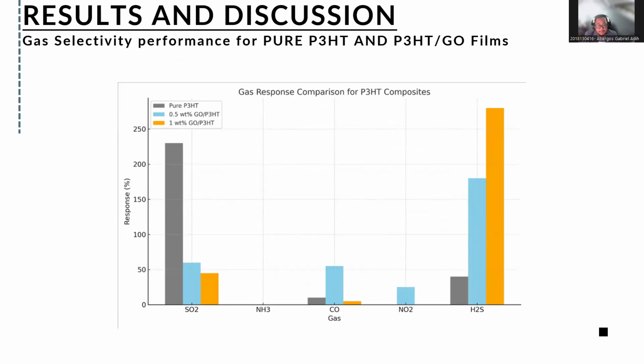So the gas selectivity performance of the pure P3HT and P3HT GO. The selectivity behavior of pure P3HT and its composites with GO reveals a distinct shift in gas response. Pure P3HT shows the highest selectivity to SO2 due to the strong charge transfer interaction between SO2 and the pi-conjugated thiophene rings, which enhances hole concentration and conductivity. However, when GO is incorporated, especially at 1 weight percent, the selectivity shifts significantly towards H2S. This is mainly due to the presence of oxygen-containing functional groups on GO such as hydroxyl and carboxyl groups.